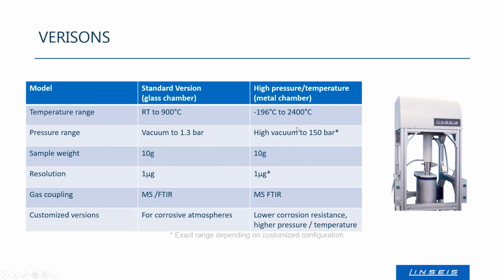As said, we customize our instruments pretty much, and this is a very customized instrument overall. So for the high-end version, it depends a little bit on the exact configuration. However, if you have the pressurized version, the metal version, the corrosion resistance is a little bit lower than with the glass version. However, you have a higher pressure and temperature range in that case.